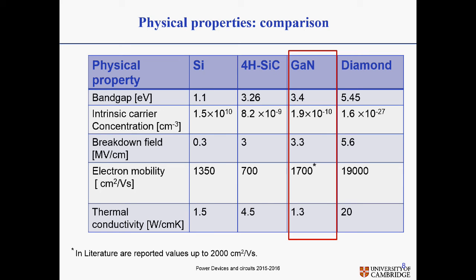What I would like to focus the attention on is the values of the band gap. So it's a wide band gap material, as well as silicon carbide and diamond. Because it's a wide band gap material, it has a very low intrinsic concentration. Look at the numbers, it's actually 20 orders of magnitude lower than the one of silicon. And the breakdown field is much higher, one order of magnitude higher than the one of silicon. And the mobility, as I was mentioning to you, the electron mobility is quite high. There are in literature values of electron mobility in the channel of the device up to 2000 centimeters squared per volt per second, as I was mentioning before.